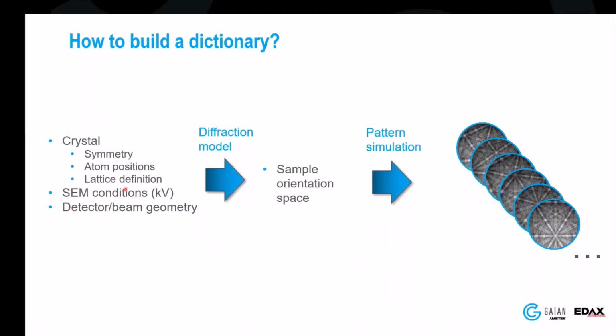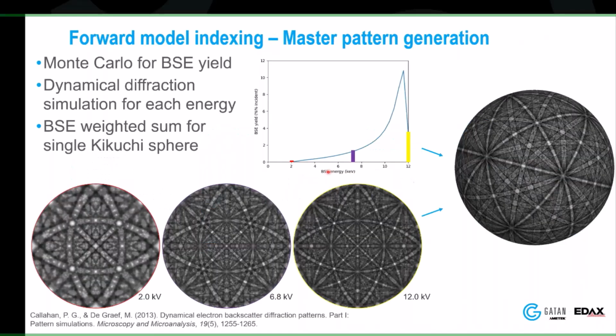So again, you start off with your system information. You run it through your modeling software, and then you get your dictionary based on how you sample your orientation space. And of course, these master patterns are created by dynamical diffraction simulations, doing the entire energy range. You would do little discrete steps, and in the end you combine all of these together to get your master patterns.